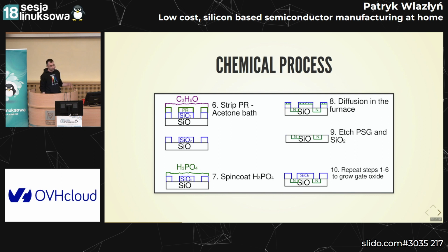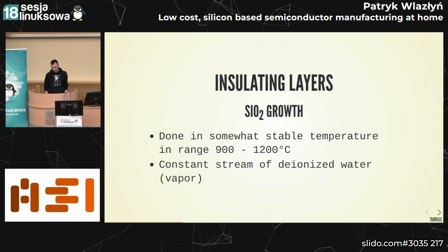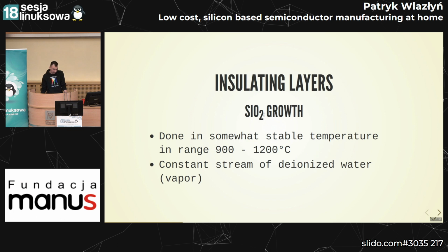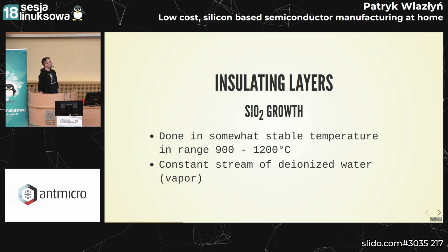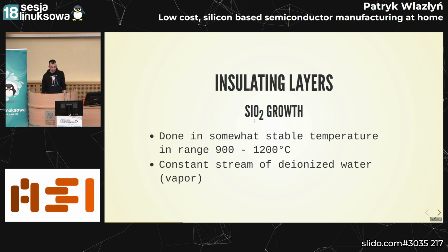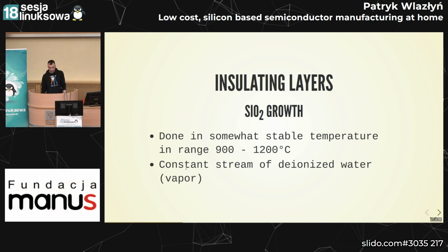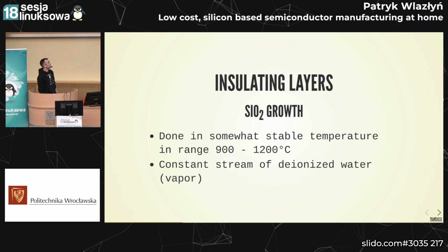And for the rest of the presentation, we'll go through how this is implemented and can be implemented cost effectively at home. So first, how to grow insulating layers. And we'll be growing silicon dioxide. You can grow it by basically sticking the silicon wafer into high temperature, and silicon dioxide will be formed by silicon grabbing oxygen atoms from the air. So you just have to raise the temperature and basically wait. If you want to do it much faster, you can also pump in a stream of deionized water. It will probably vaporize at these temperatures. And for some reason, having water molecules in the air instead of just dry air makes the process much faster. So the growth is much faster.